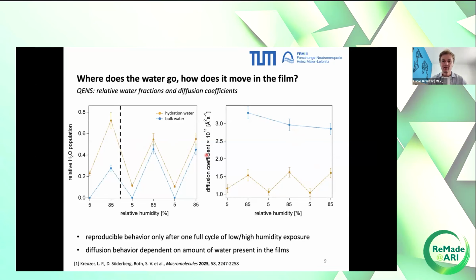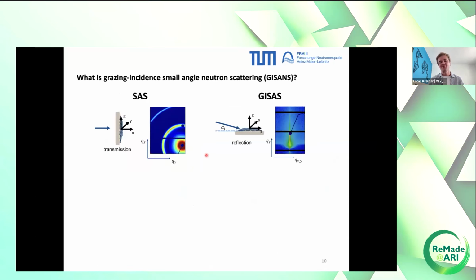So we have a pretty good idea what is actually happening in these films. And now comes the last part. Now we want to correlate this to the nanomorphology. And this we can do with another neutron technique, small angle neutron scattering, which you usually measure in transmission mode.